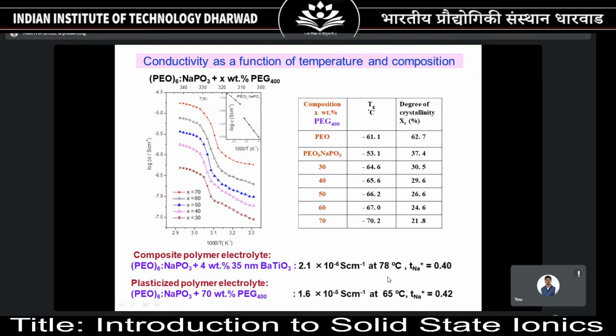I'm saying 3 because I'm no longer measuring the ionic conductivity at 78 degrees Celsius. I'm measuring at 65 degrees Celsius, and I'm getting a conductivity of the order of 10 to the power minus 5 Siemens per centimeter. So this is a typical classic example where you can change the conductivity of crystalline metaphosphate, which was an insulator. Now it has an ionic conductivity of the order of 10 to the power minus 5 Siemens per centimeter. A huge, drastic change in ionic conductivity.